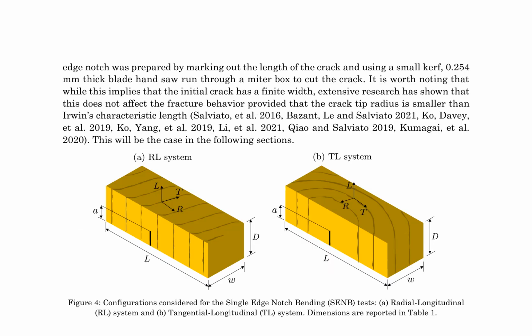This study examines the fracture behavior of wood samples using the single-edge notch bending (SENB) test, focusing on the radial-longitudinal (RL) and tangential-longitudinal (TL) configurations. To create a finite width edge notch, a small kerf blade hand saw was employed, ensuring the crack tip radius is smaller than Irwin's characteristic length to avoid affecting fracture behavior. The SENB test configurations, illustrated in Figure 4, comprise the RL system, where the crack propagates parallel to the grain in plane LT, and the TL system, where the crack propagates parallel to the grain in plane RL.